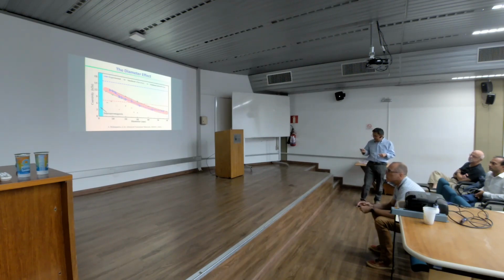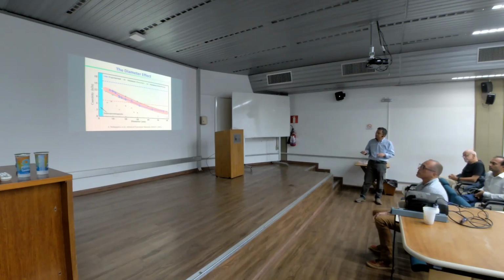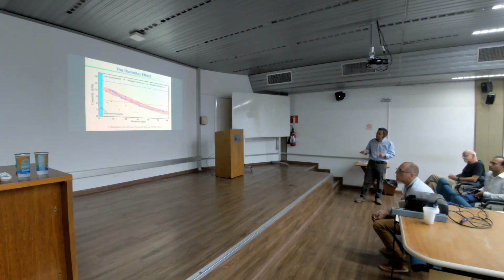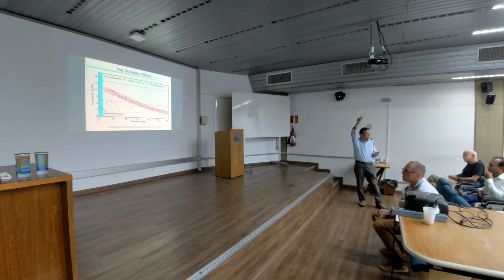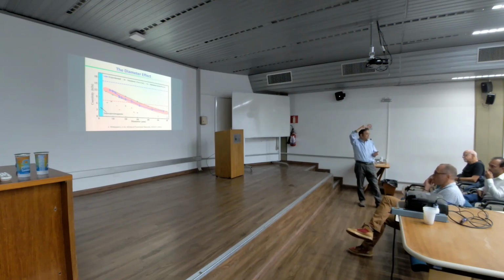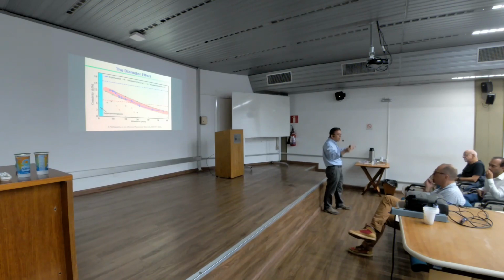Before I published these results, I met a theoretical simulation group in a TMS meeting. They had already done this simulation. Later on, a Chinese group also did this simulation, which has good consistency. So basically, if we count the experimental error bar, this belt shows the coercivity ceiling. What that means, I hope I can explain it clearly, is that any sample has geometric conditions, right? Any sample has a shape. If you have a shape, your shape already gives the coercivity ceiling of your sample, of your magnetic hardening.